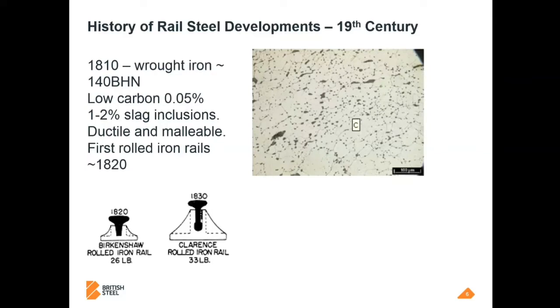The trouble with these rolled iron rails, and you can see there's a couple of diagrams in the bottom left, they sat in a cast iron shoe, and the cast iron shoe was the preferred method for affixing them to the sleepers and holding them upright on these early rails. But the problem with these low carbon steels is that they have relatively low strength, and locomotives, heavy contraptions, as we discussed earlier, are getting heavier as well. As time passes, they're more powerful, heavier loads being pulled, and you quickly overwhelm the material strength.